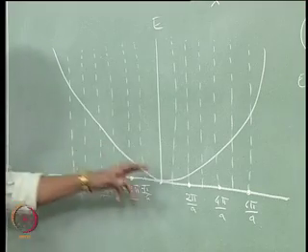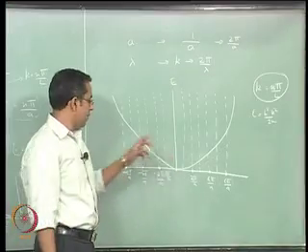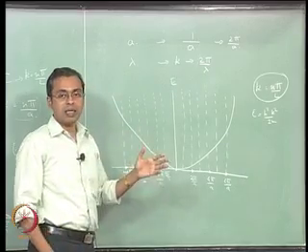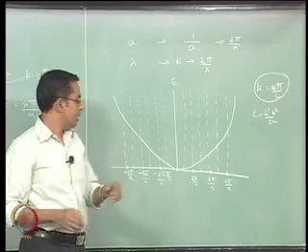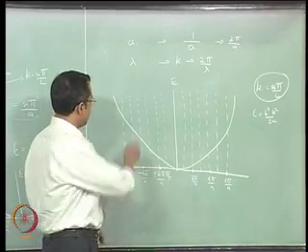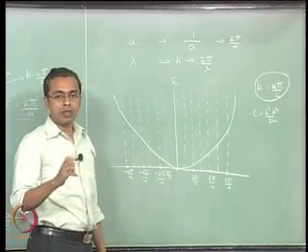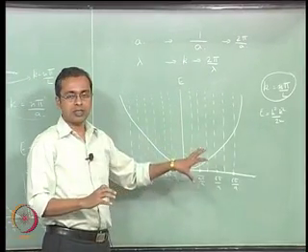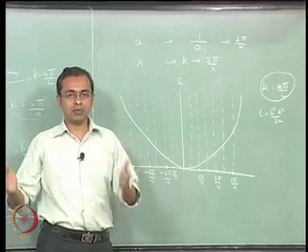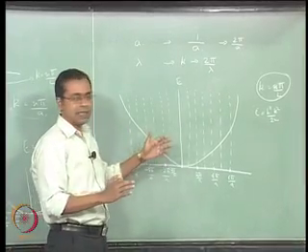So at all of these locations diffraction is occurring, and wherever diffraction occurs it turns out that certain energy values become forbidden, alright. So at Brillouin zone boundaries this E versus k relationship begins to distort, okay, and it is a result of this distortion that results in the band structure of the material, okay. Right now I am saying that in a general sense.